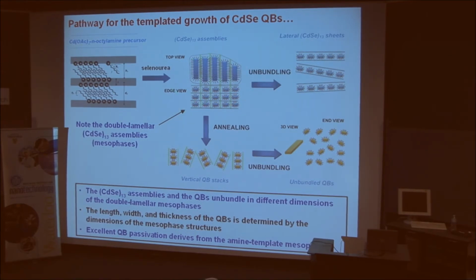I wish we knew how to control the lengths or the widths of these sorts of structures, the widths and the thicknesses. We don't know how to do that yet, but that's clearly what's defining these quantum belt-like morphologies. And furthermore, I imagine, or I propose, that the excellent passivation of these top and bottom surfaces is due to the formation of self-assembled amine monolayers on the top and bottom surfaces of these belts within the template structure.